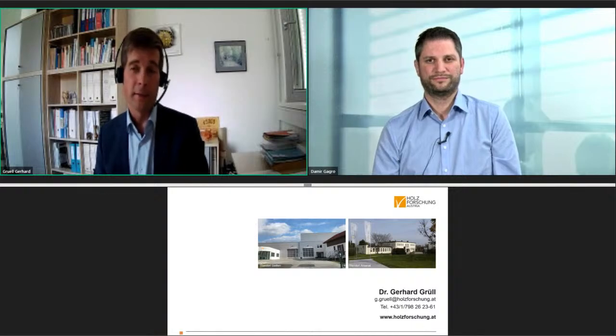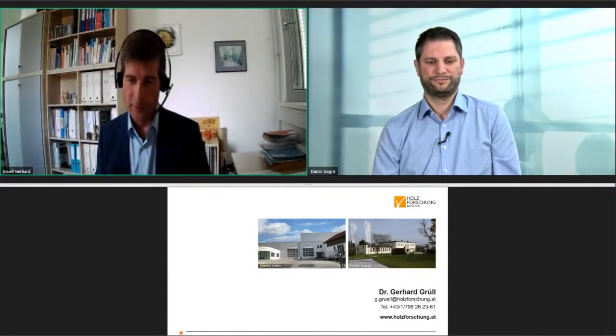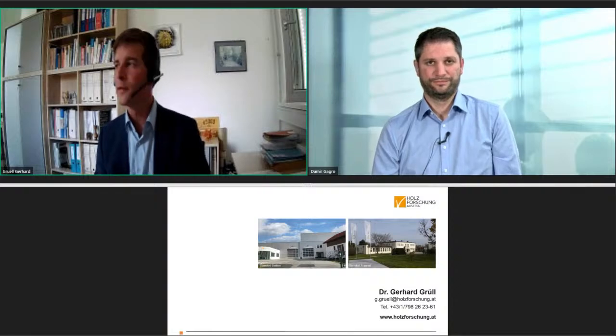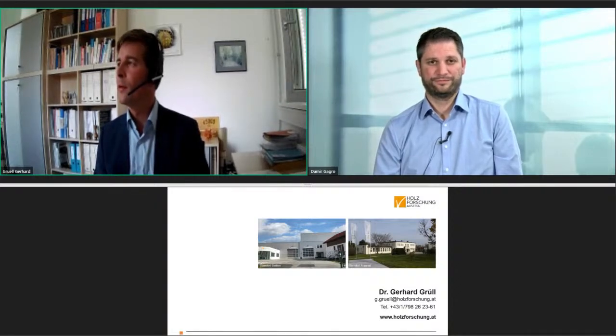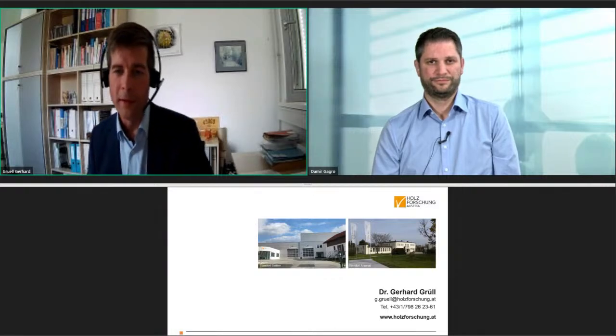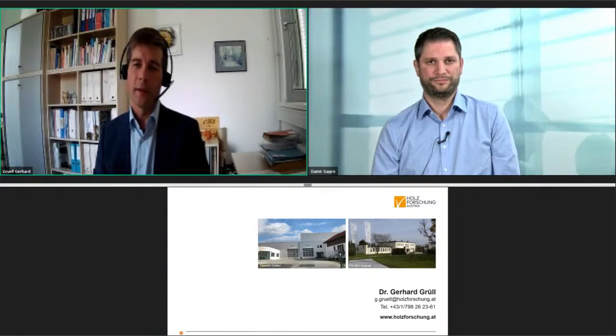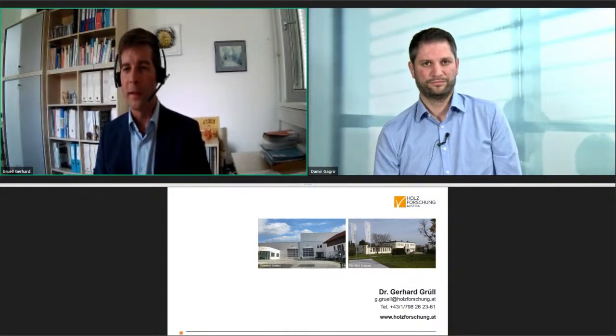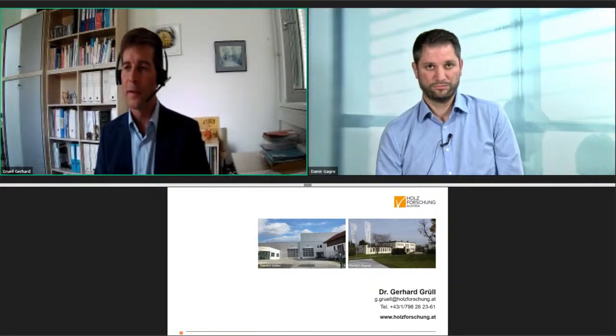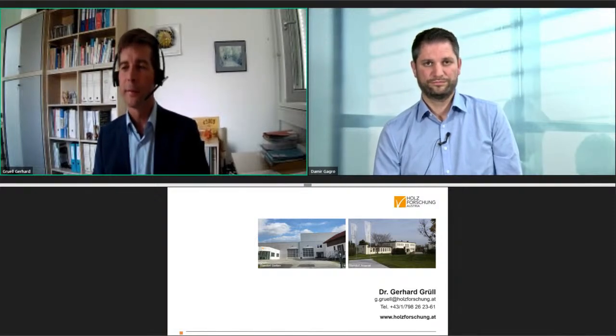Maybe I haven't tried this for exterior coating so far. We've done a lot of studies with additives without varying the matting agents in coatings. But for interior coatings, we got this experience with a study with persons touching and looking at surfaces, and they figured out that a matte surface is very important.